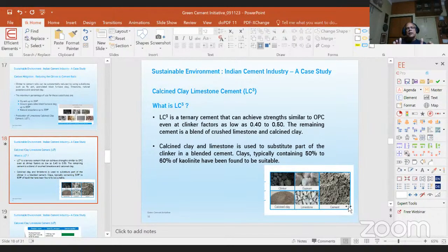So clay is typically containing 50 to 60% of the kaolinite. Now, but for that, you need very special type of clay, which will have 50 to 60% of kaolin. And in India, we have found there are clay deposits in Rajasthan. They have found something in the northwest part of India. But these reserves need to be very carefully investigated. The clay needs to be carefully investigated, analyzed, and only if it is found suitable, it could be partially calcined and then can be used as LC3.